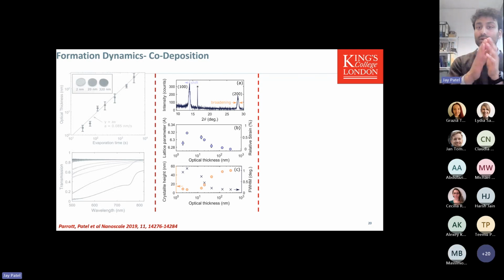Do they instantly form small little islands? Do they form structures which are strained? Or do they form something which is just an amorphous blob? What we found is that the reaction induces a crystalline product that's formed on the surface, of varying sizes, as you can see in the bottom graph where it says the crystallite height. You can see that it slightly increases, but at the very initial stages, it all stays pretty much the same.